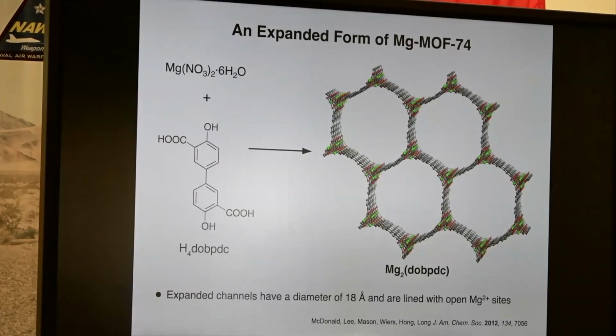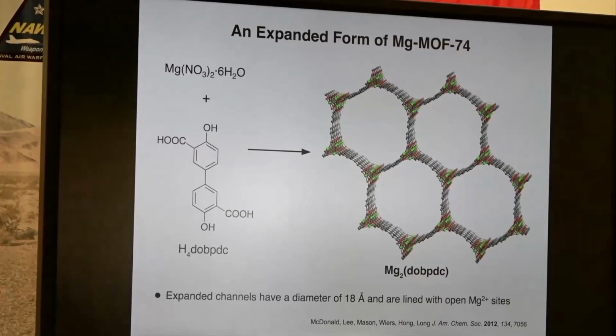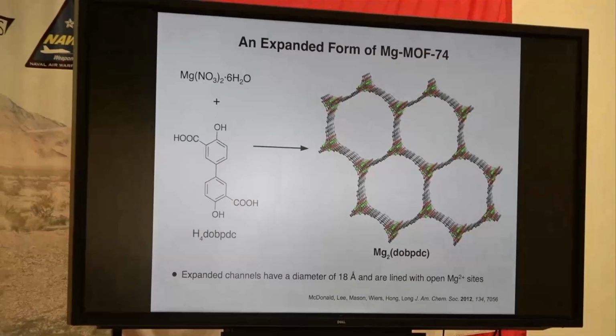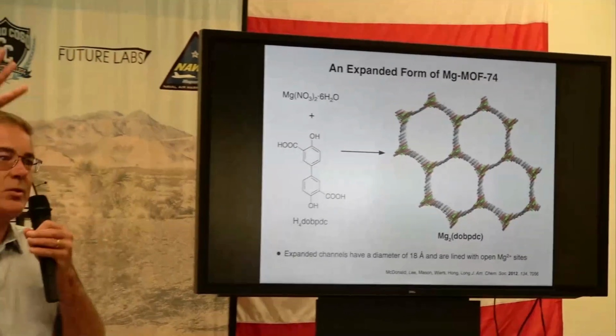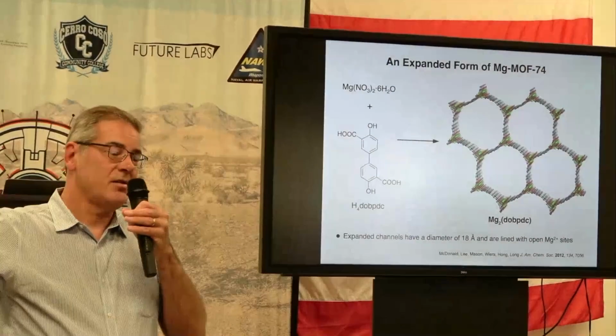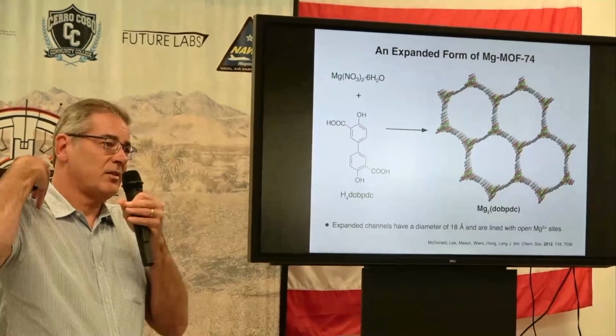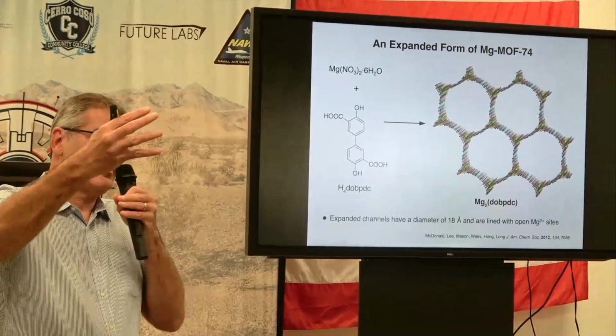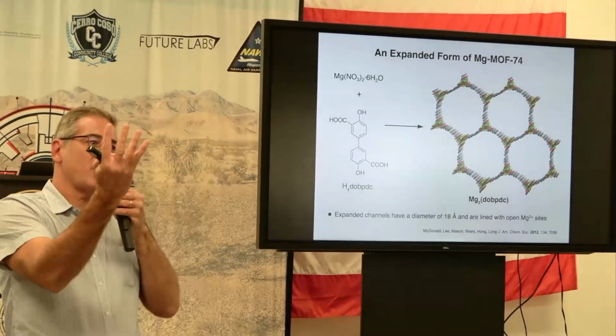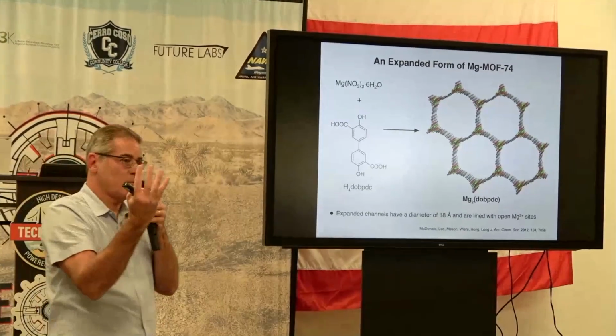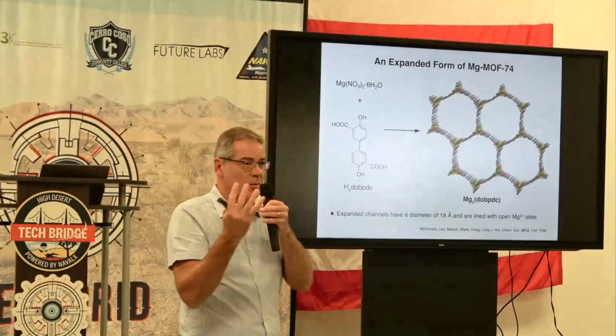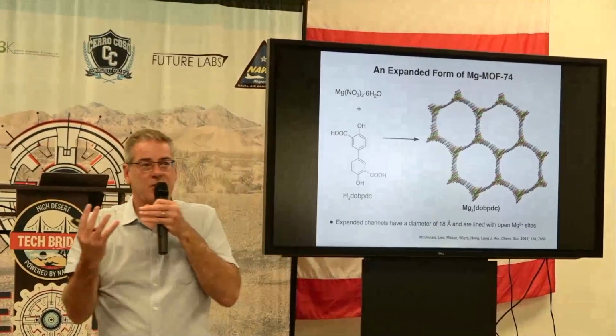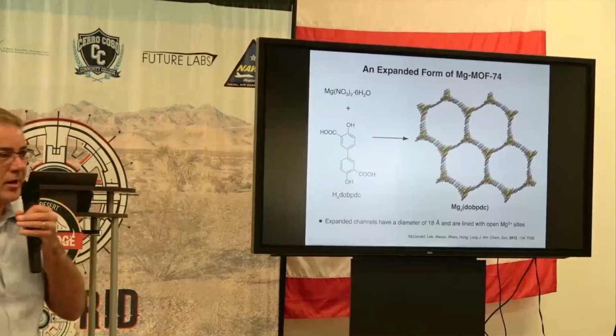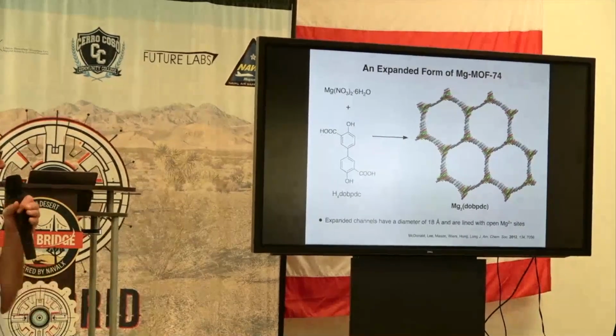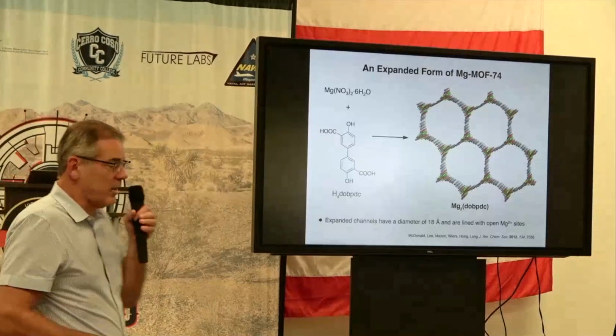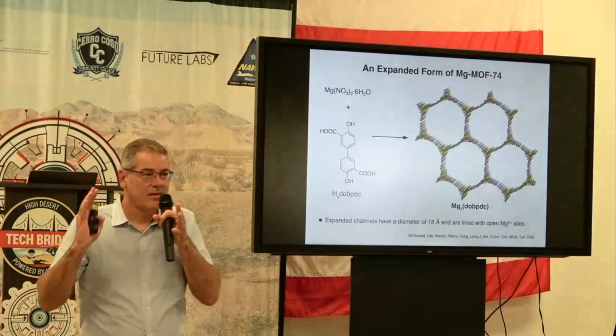So here we're reacting this magnesium salt with this organic linker. We've got 2 hydroxyl groups and 2 carboxylic acids. That linker will be deprotonated 4 times, and that 4- anion will stitch the magnesium cations together to form a honeycomb type structure. So at the right, you're looking down the channels in the honeycomb. These channels are about 18 angstroms across.